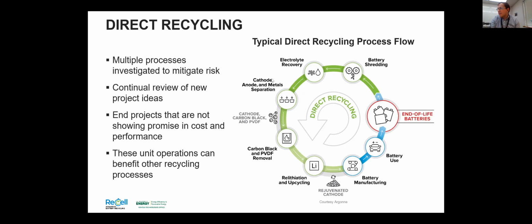Then you have to separate everything. This is very challenging, but there are good methods now that we've developed along with others in the community to actually separate all these materials. You then have to take your cathode material that contains this carbon and binder called PVDF, and get that off and clean that up. And then you actually have to add back some lithium. I know Noah mentioned the solid electrolyte interface. You lose a lot of the lithium into that stuff that forms on the graphite, so you actually have to replace that lithium. And then maybe you have to do some chemistry changing to try to get it up to the current specs of the day. And then that goes back into battery manufacturing.